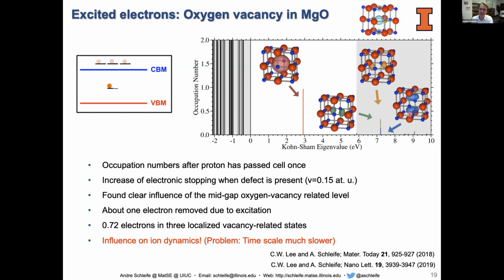It actually went into an excited state, three-fold degenerate, and all of these three states are sort of like excited states of the defect, as we see again from these partial charge density plots here. So in other words, what happened is the proton comes and excites the defect, and the defect is in an excited state. And so the question that we then asked is, how does that affect the motion of this defect itself? Like what does the oxygen vacancy do as a result of this being in this electronic excited state?